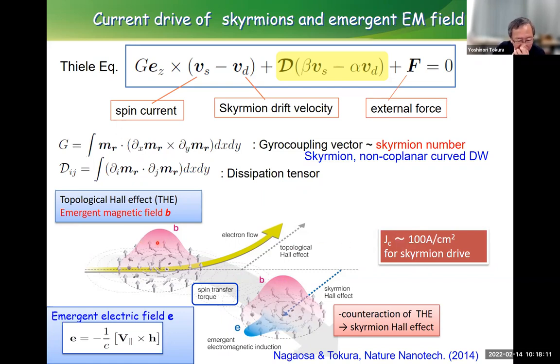And if you have skyrmion motion here, it's interesting. First, the electron flows, and then according to this theory equation, spin transfer torque is applied, and the skyrmion tends to move. Also the electron is deflected by this emergent magnetic field, which is carried by the skyrmion. So because of the counteraction of the electron topological Hall effect, the skyrmion also moves in another direction. This is a combined motion of the translational and this Hall motion. So this is called the skyrmion Hall effect. This skyrmion Hall effect is really observed in many material systems.